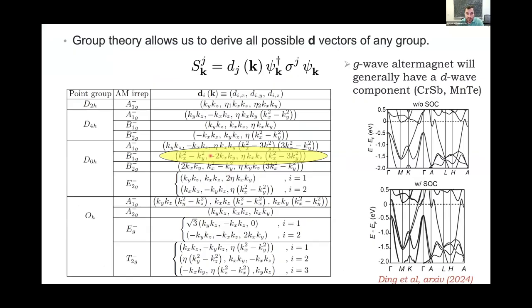There are other interesting effects. So you can do this classification for any group, any irreducible representation. It turns out that sometimes some spin components will acquire different angular momentum form factors. So the case that actually is relevant for chromium antimonide and manganese telluride is that these are g-wave altermagnets. But when you turn on spin-orbit coupling, especially for chromium antimonide, where the moment points out of the plane, the in-plane moments now acquire a d-wave form factor. That is the only thing present at k is equal 0, for example. Okay?